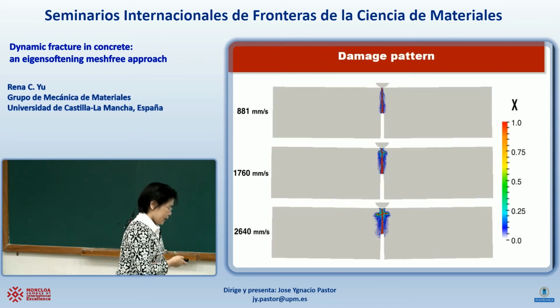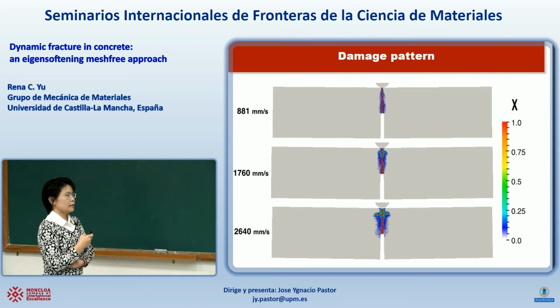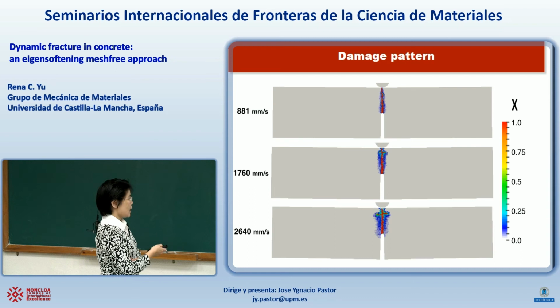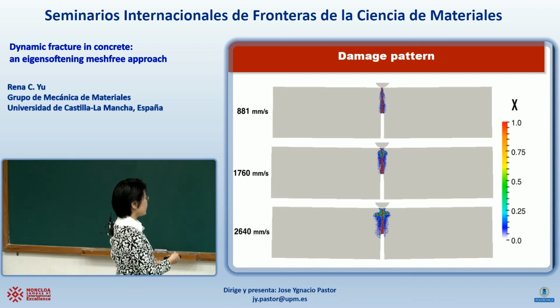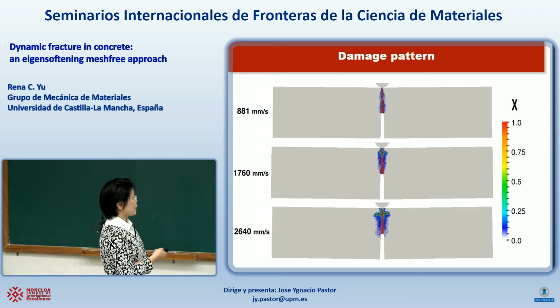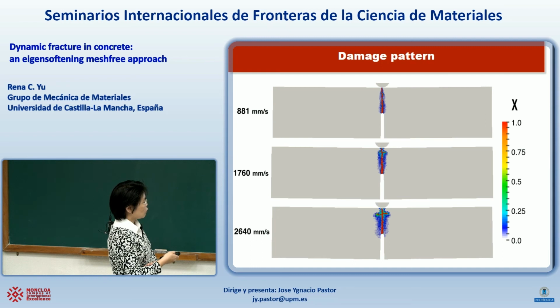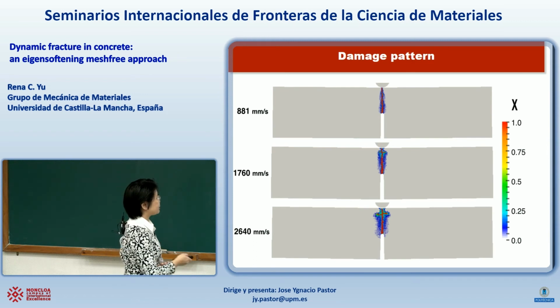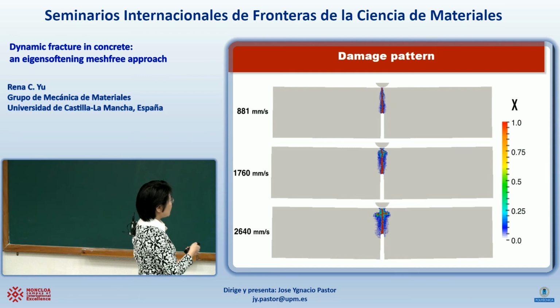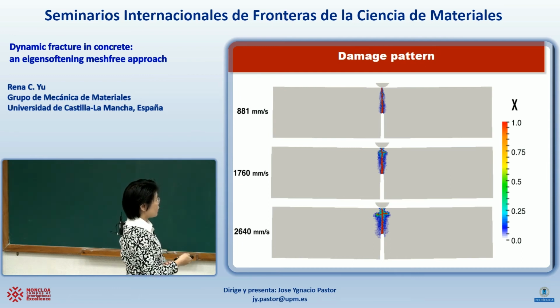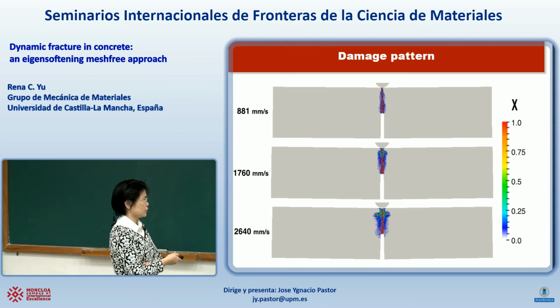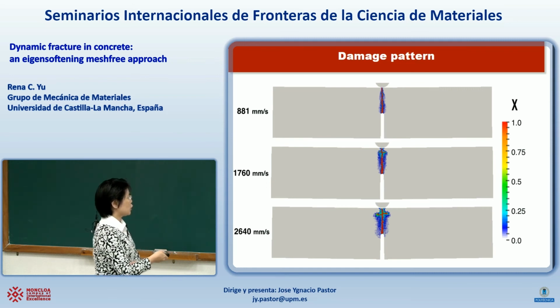See? And since this is a mode 1 crack, we know that it's going to predict a straight crack. And we would like to see, for the 3 different velocities, what the damage pattern is. What you see here is that 1 is when the material does not resist anything, and 0 is when it's still perfect. So we see here that when the velocity increases, you have a bigger area of damage. And additionally, you have 2 cracks. Actually, this is something that is expected from the previous calculation. We also observed branches like this.